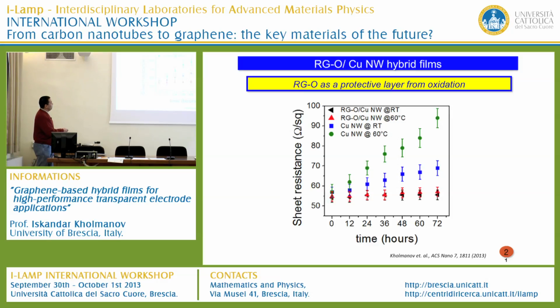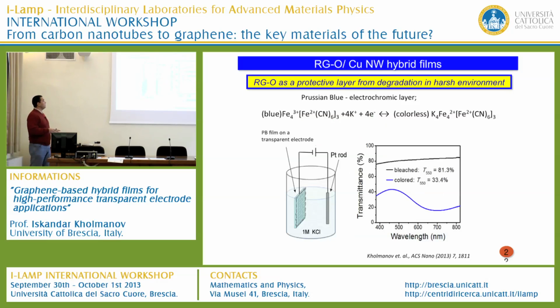But when we use the hybrid film, the nanowires coated with RGO, there is no significant change in sheet resistance over this time range. So it demonstrates that RGO can protect the copper nanowire film from oxidation. It is also a protective layer against degradation of copper nanowire films.